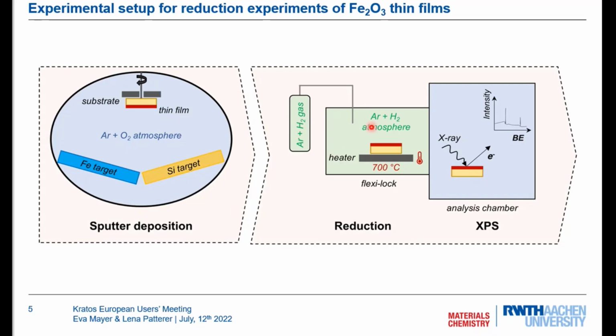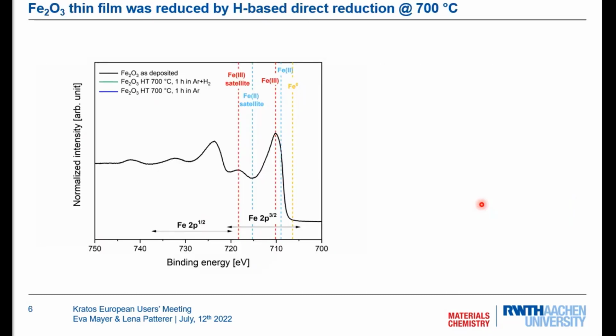So we model it in our flexi-lock in our XPS chamber. So we have this gas inlet, so we can create an atmosphere of argon plus hydrogen. So we don't have pure hydrogen because it can be quite dangerous, so we use a mixture, and then we heat up our model system of the thin film to 700 degrees C, and look at the reduction kinetics of our thin film, and analyze that without breaking the vacuum in our XPS analysis chamber. And the first results of this project are now presented by Eva.